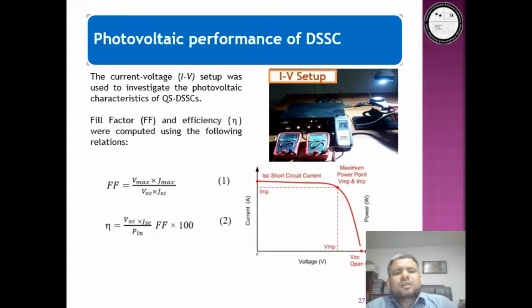The current voltage setup was used to investigate the photovoltaic performance of solid state DSSC under the light intensity of 100 milliwatt per centimeter square. So maximum current density, short circuit current density, maximum voltage and open circuit voltage were calculated from JV curves, while the fill factor and efficiencies were computed using the following relations. That is, fill factor is equal to Vmax into Jmax divided by VOC into JSC. So efficiency is equal to VOC multiplied by JSC divided by power input, into fill factor.